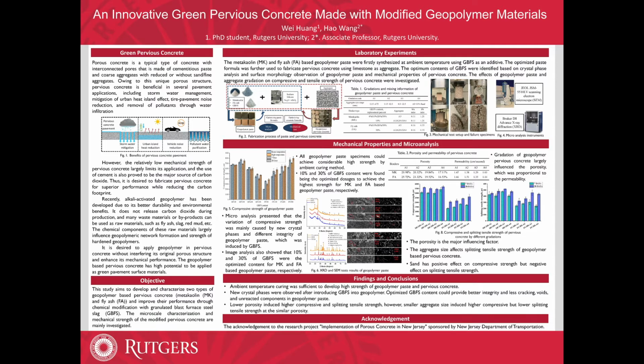In general, we found the ambient temperature curing was sufficient to develop high strengths of geopolymer paste and pervious concrete. And also we found new crystal phases were observed in the XRD result after introducing the GBFS into geopolymer. And also we found the optimized GBFS content could provide better integrity and less cracking, voids, and unreacted particles in the paste materials, as we can see from the SEM result.